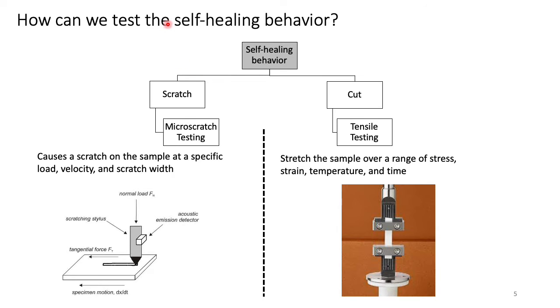So how can we test the self-healing behavior of block polymers? This depends on the type of deformation that is made on the material. If it's a scratch, for example, we are going to use micro scratch testing, which is a device that causes a scratch on the sample at a specific load, velocity, and scratch width. And if it's a cut, we're going to use tensile testing, which stretches the sample over a range of stress, strain, temperature, and also time.